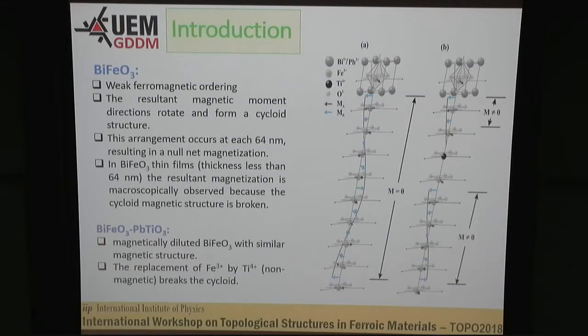Okay, BiFeO3, bismuth ferrite, is a very well-known prototype phase for multiferroic material. It has a weak, but still there, coupling between the order parameters, electric and magnetic, magnetoelectric coupling. And if you use another prototype ferroelectric material like lead titanate, you can dilute this lead titanate in BiFeO3 with a similar magnetic structure. The case here is that you break the cycloid period that prevents the microscopic magnetization in BiFeO3